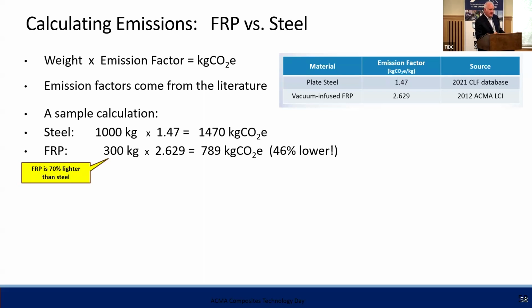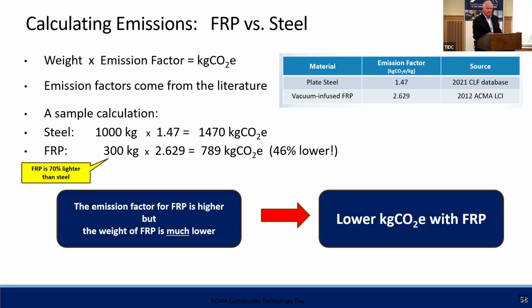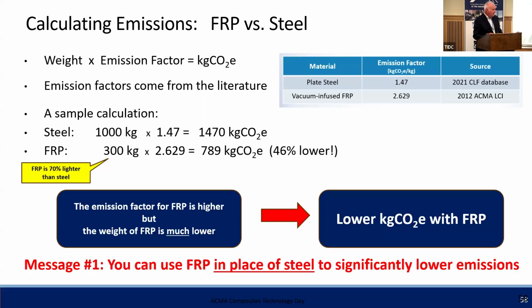Now let's do the same thing for FRP. And this is where the weight difference between steel and FRP becomes important, extremely important. Because instead of a 1,000 kilogram part, FRP is 70% lighter than steel. So you only have a 300 kilogram part. And now you multiply it by this emission factor up here for vacuum infused FRP, and you get 789 kilograms of CO2 equivalents. That is 46% less than the example with steel. So the emission factor for FRP is higher, but the weight of FRP is much lower. And when you calculate that product, you get lower kilograms of CO2 equivalents with FRP. So this is sub-message number one, that you can use FRP in place of steel to significantly lower emissions.